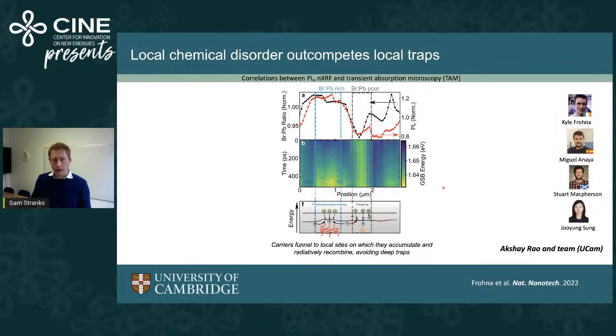And I'll give an example of that. This is looking at a section of a film, a line profile of a film, and tracking across that the halide content. In black, this is showing the bromine ratio, and in red, this is showing the luminescence quantum efficiency. What that's saying is that where it's bromine rich, we have more luminescence, and where it's bromine poor, we have less luminescence. And that agrees with the result I just showed in the previous slide.